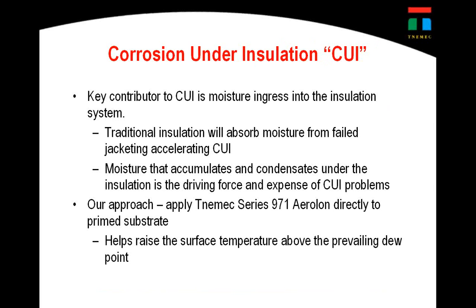Okay. Next conversation obviously is corrosion under insulation. The key contributor to CUI is moisture ingress into the insulation, which obviously when you get moisture in your insulation, you automatically lose 60 to 70% of your insulated value. The traditional insulation will fail from jacketing, accelerating the CUI. So when we get air and moisture underneath insulation, we get an accelerated corrosion effect taking place. Moisture that accumulates and condenses under that is a driving force behind the CUI.